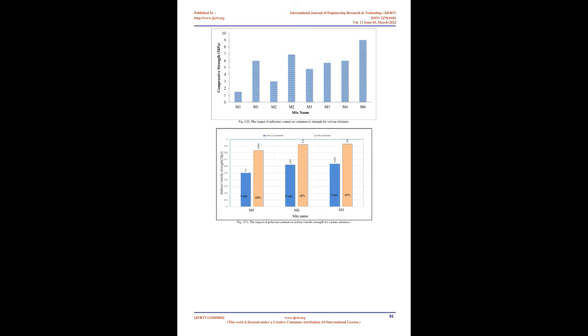The test results demonstrate that by increasing the cement content from 200 kg per cubic meter to 350 kg per cubic meter, the compressive strength at age 7 days increased by 300%. This can result from the comparison between mix 1 and 4.